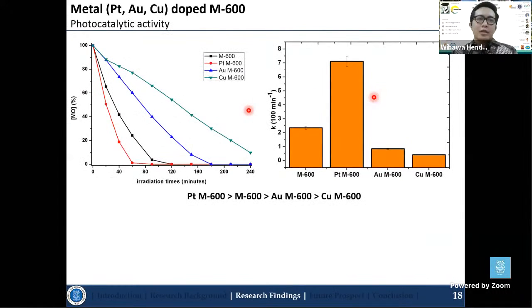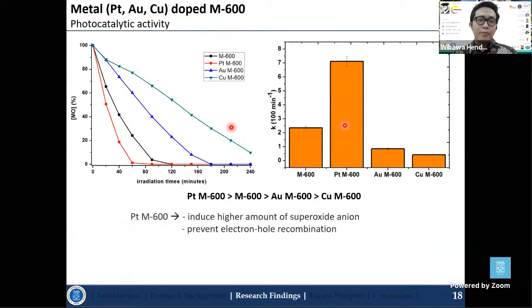So based on the photocatalytic efficiency here, it can be seen that the platinum deposited on the M600 gives the best photocatalytic activity compared with the M600 because it can induce a high amount of superoxide anions, which are reactive oxygen species, as reactive radicals, which play roles in the dye degradation.